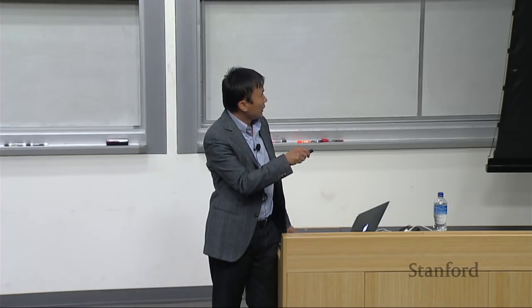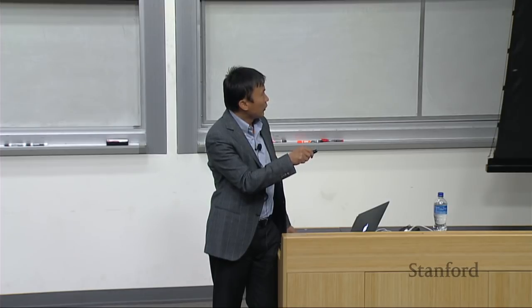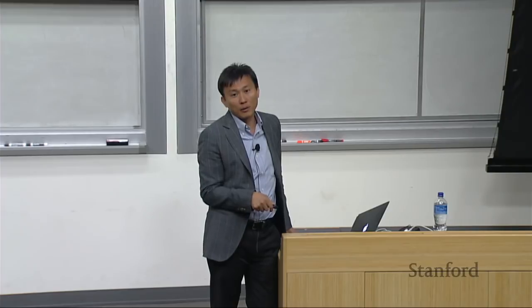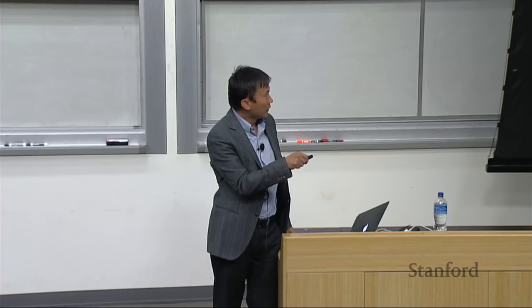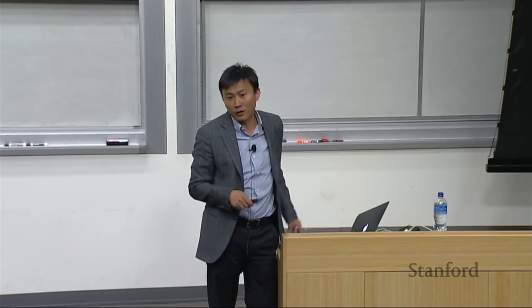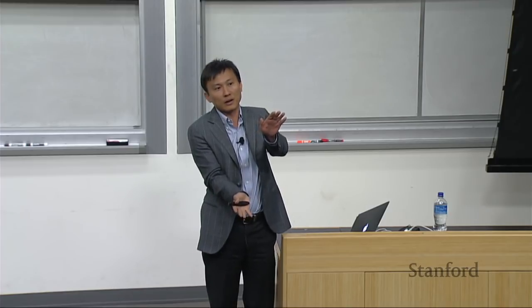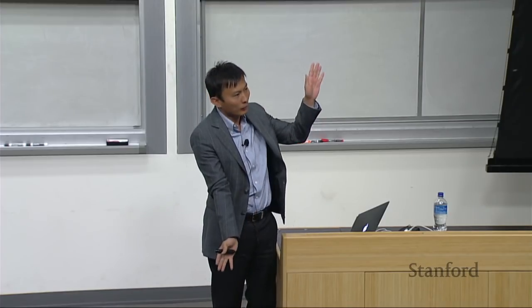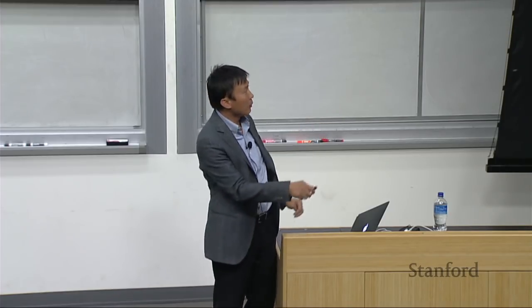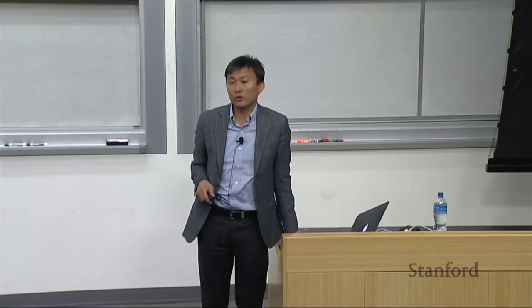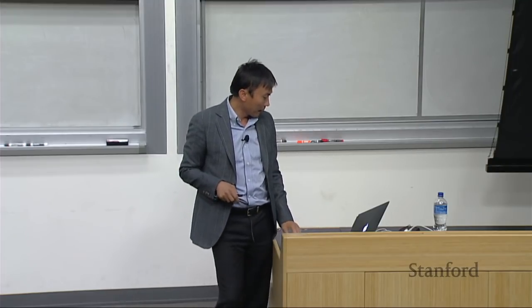Making these plating and stripping cycles, this is the voltage profile. This smaller one tells you it's stable. The blue color is stable. The red color is the regular lithium foil. The voltage opening up is telling you you need to use higher and higher overpotential. It becomes less and less stable. So we now have a solution that's a lot more stable.